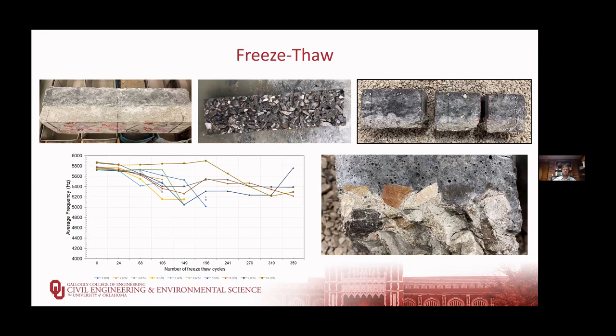But looking at those composite specimens, we found that in every case, we had deterioration in the base concrete before we had deterioration of the interface. And even for the 0% fiber specimens that are shown on the top right, that cracked transverse to the specimen, the interface between the two concretes was still in very good shape.